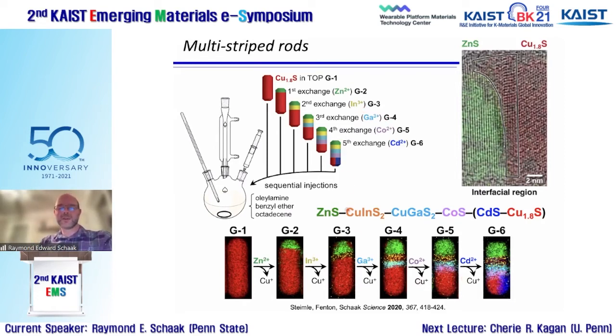So our next exchange step is indium that forms a band of copper indium sulfide below the zinc sulfide. Next exchange is gallium that installs a segment of copper gallium sulfide. Next is cobalt that installs a segment of cobalt sulfide. The next is cadmium. Remember, cadmium sulfide is the one that's bigger than typically all of the others. So cadmium sulfide wants to have an interface that's this direction. So we get these segments that are horizontal interfaces, zinc sulfide, copper indium sulfide, copper gallium sulfide, cobalt sulfide, and then a cadmium sulfide notch on the side.